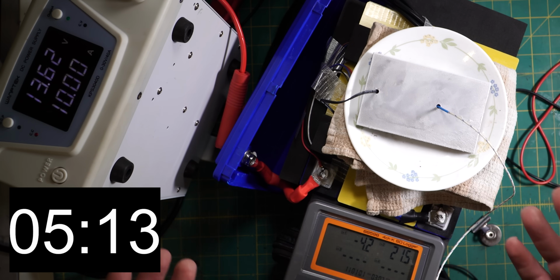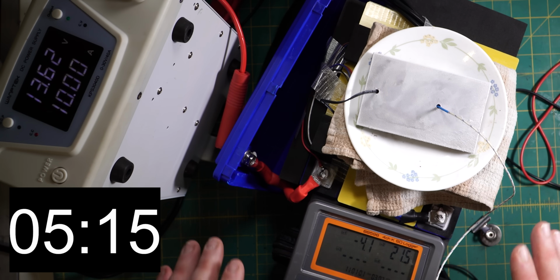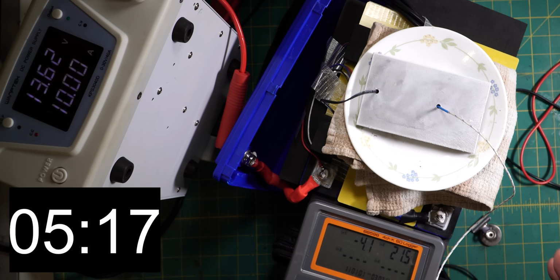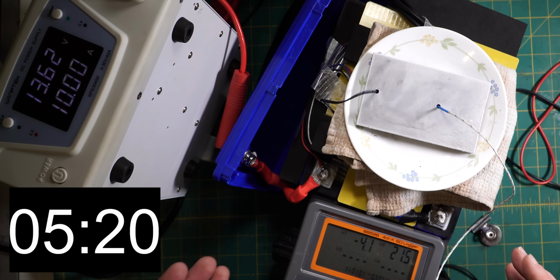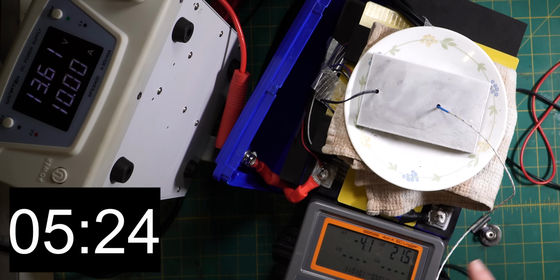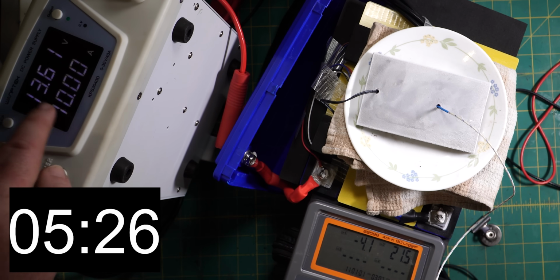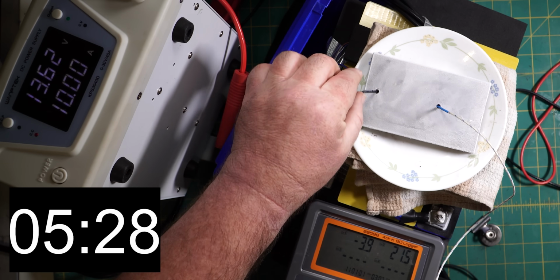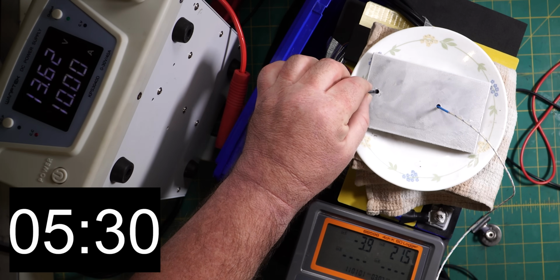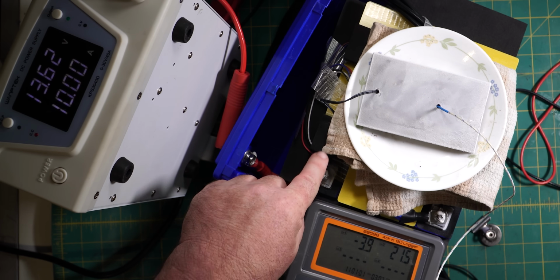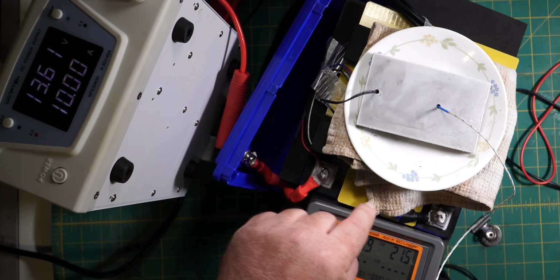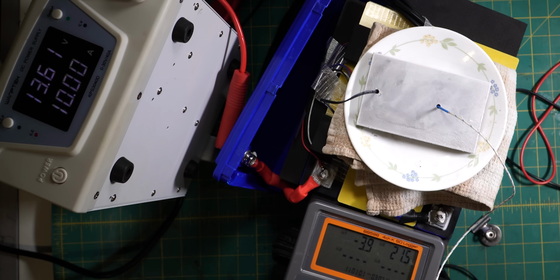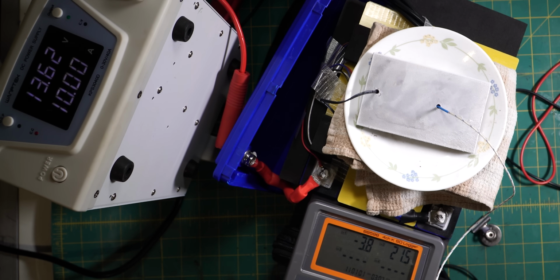Okay, well it looks like we have our first issue, and that is low temperature charging protection. The plate has now risen from nearly negative 10 to negative 4.5. Still sitting at about 21.5 degrees ambient, and this thing is still taking 10 amps, even though we've had good contact with the thermocouple probe from the BMS from the cell temperature to the metal plate there, and it's still charging. That's an issue, because if we charge below 0 degrees Celsius,